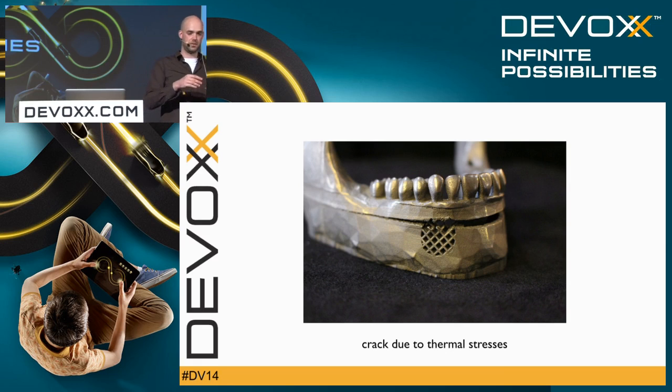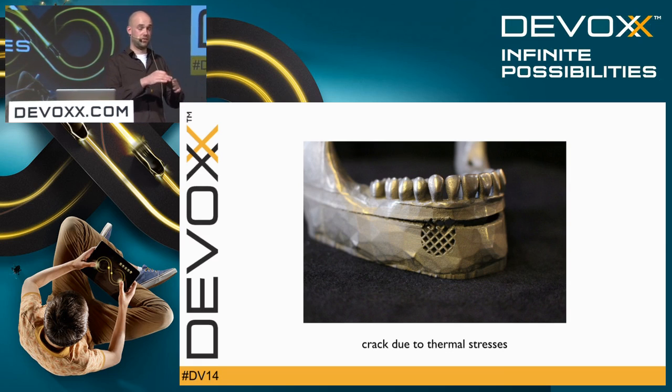If you heat up a part by a laser very fast, it will get hot, it will melt, it will expand. And after a fraction of a time, you will cool it down, and it will contract once more. So you get expansion and contraction, meaning you will induce thermal stresses inside of your part. If you don't get it under control and you don't take it into account, you will end up with this kind of failure. You do not want that this happened when it's also being implanted in a human body. That would be very bad. That's recent research also at the KU Leuven.